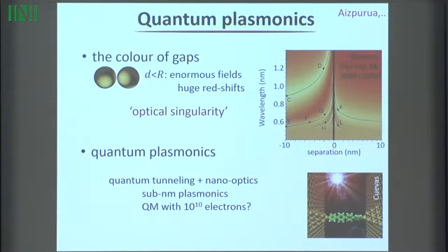It gets even worse because as I bring these closer and closer together, what should happen is this mode should head off into the red forever. And of course that doesn't happen. The reason it doesn't happen is because when it's close enough, actually electrons can quantum mechanically tunnel through the gap. And when they quantum mechanically tunnel, they basically discharge this capacitor which is existing from these two interfaces. So that's a quantum mechanical effect that I can see at room temperature in ambient conditions as long as we can look at the gap.